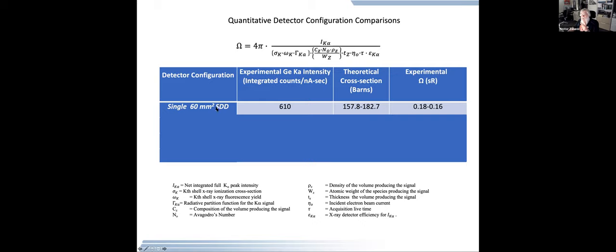And I can go to my single 60 square millimeter SDD detector. I can measure the integrated counts per nanoamp per second. I know the cross sections. I can figure out what the solid angle is. And if you remember that curve I told you before, we were somewhere around 0.1, 0.2 steradians. That's right. It's about the value we get.